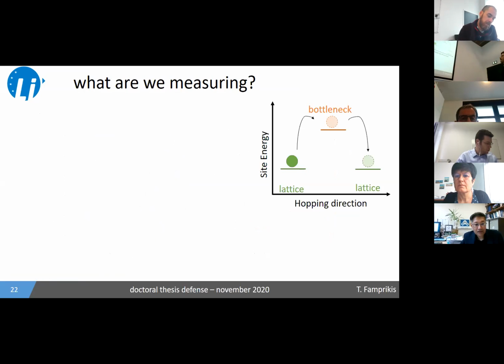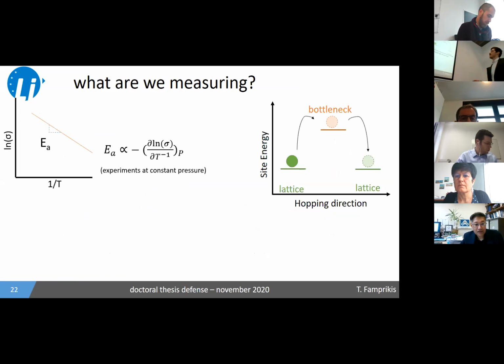So I will try to explain this through this simple energy diagram of an ion hopping from one stable lattice site to the next through a high energy bottleneck, the difference between the two being the activation energy. So in order to measure the activation energy, we commonly do experiments as a function of temperature. We plot them like this in Arrhenius coordinates, and the gradient is then the activation energy. Basically what we're doing, if you think about it, is by changing the temperature, we're changing the average available energy that we give to the lattice ion for a hop.